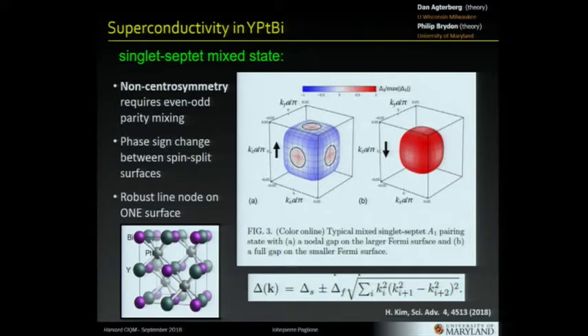And they're actually shown here in the calculation. This is the spin up and down Fermi surface with the color showing the size of the superconducting gap, negative and positive, so it changes sign. It actually changes sign on one of these surfaces here, and that's the black line. So that's a line node in the superconducting order parameter. It's amazing. When they showed me this, I said, no, you just drew that, right? No, they got it from calculation. It's quite neat.